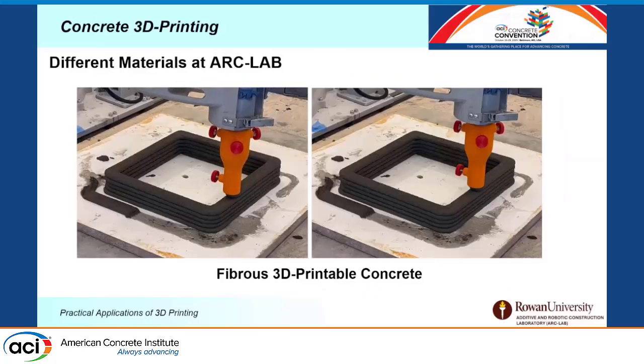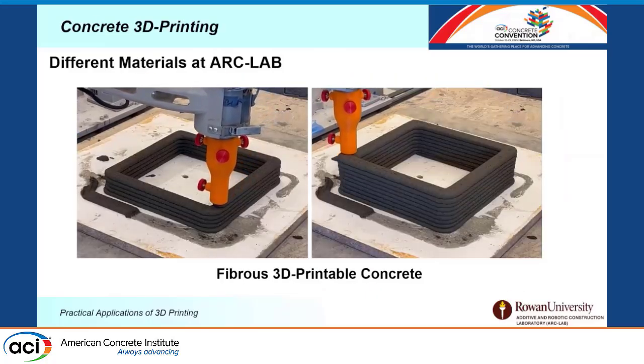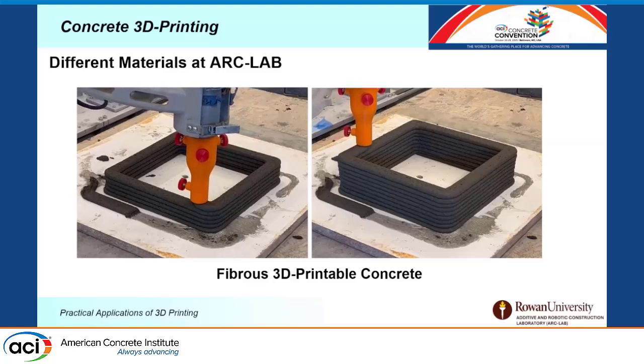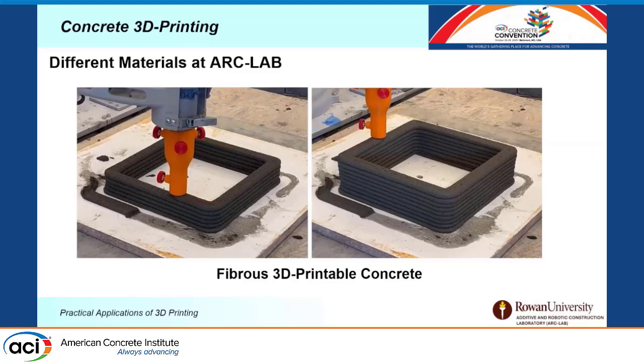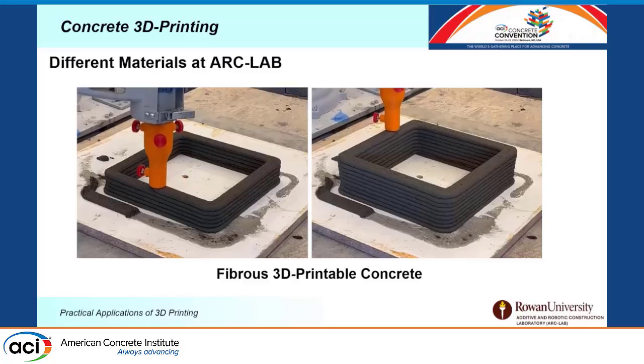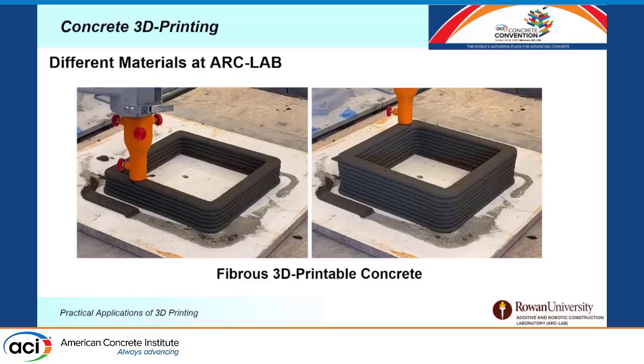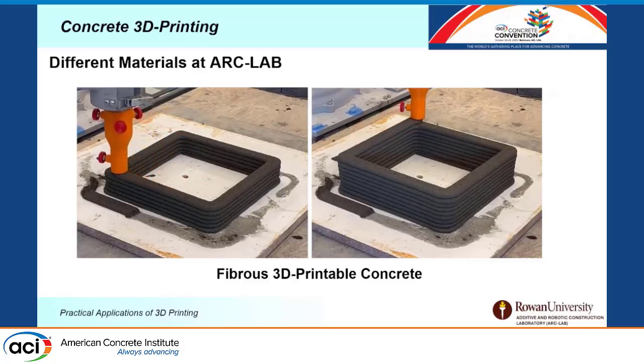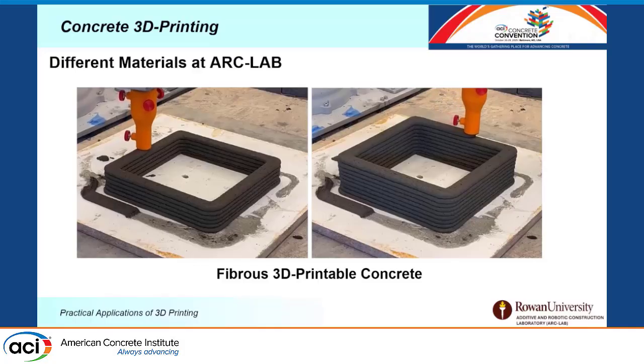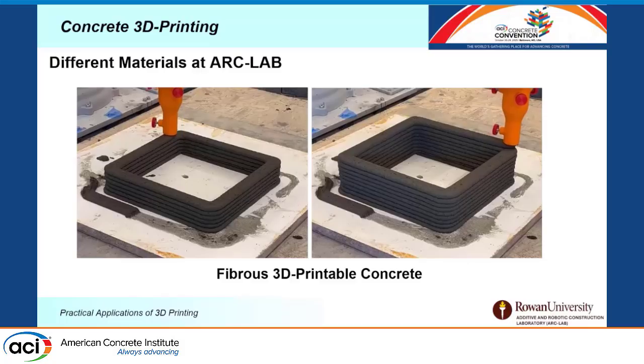We also examine and develop mixes that incorporate steel fibers. Those are smaller steel fibers, 6 millimeter, 4.5, and 13 millimeter. In some mixes, we were able to get to 1% by volume. And you can see here the material is extruded with fiber within it, and the quality of the material is a little bit compromised because of fiber alignment, etc. You can see some porosity on the interfaces.